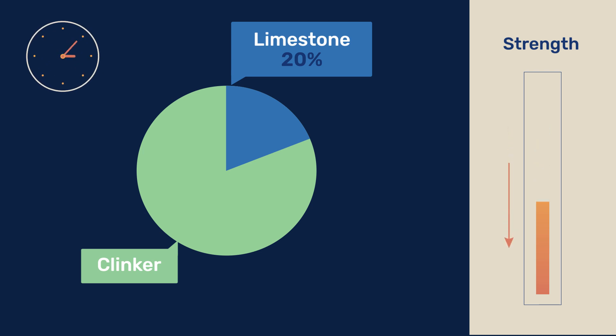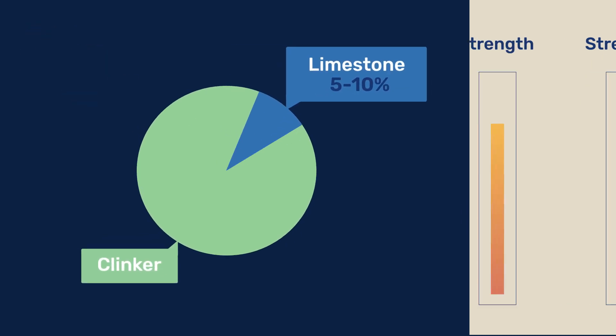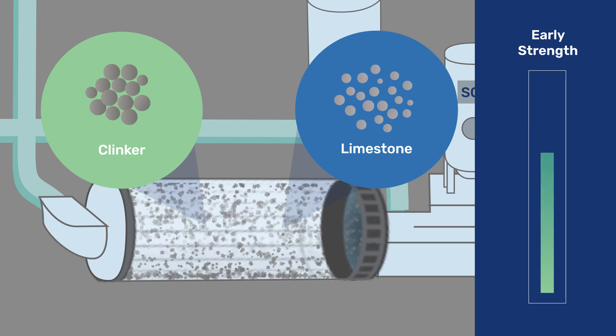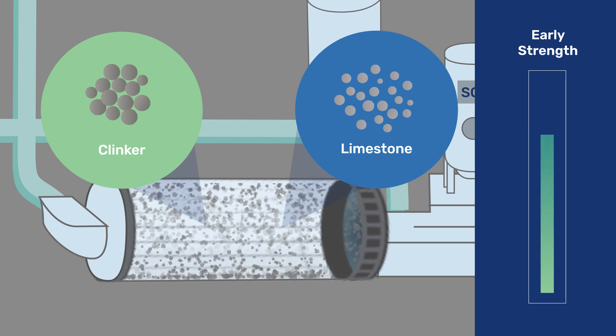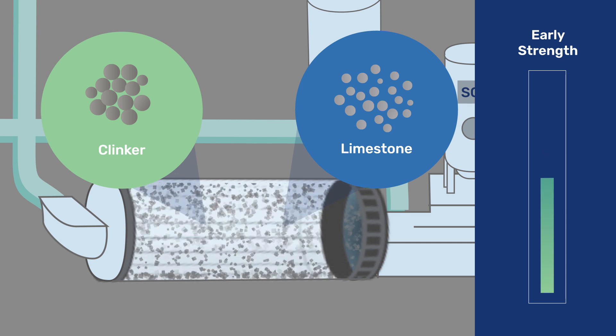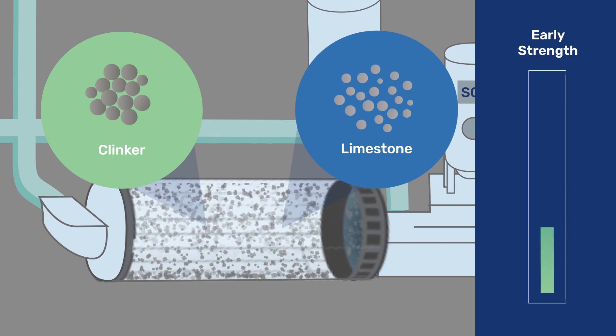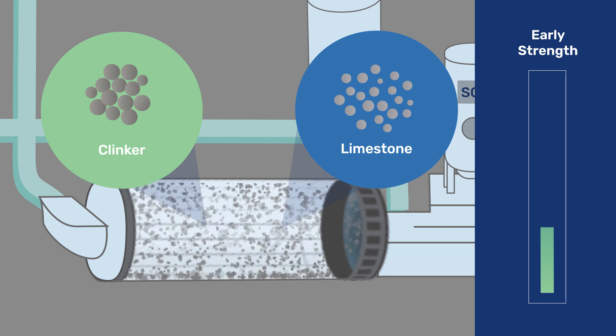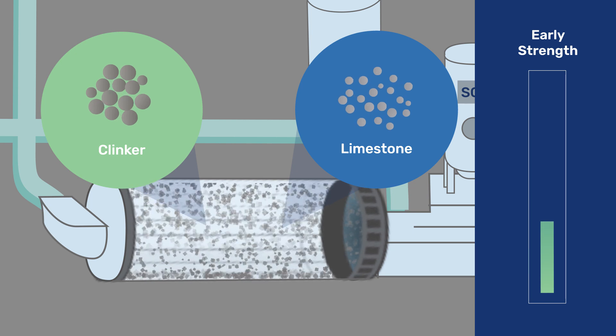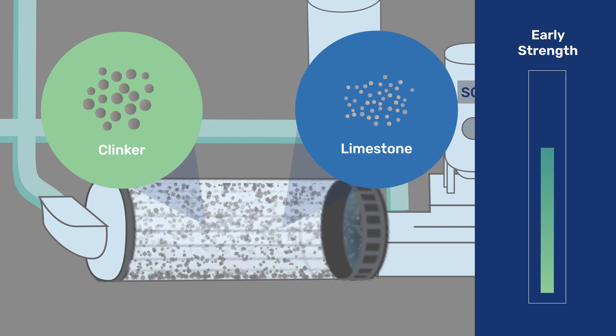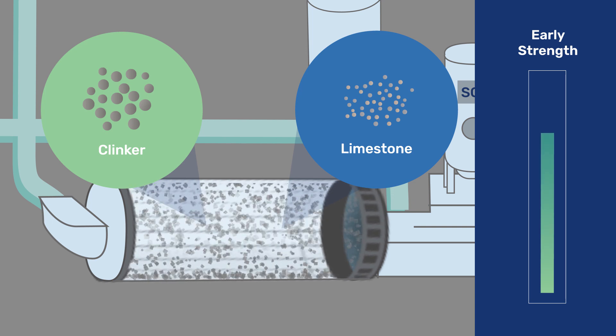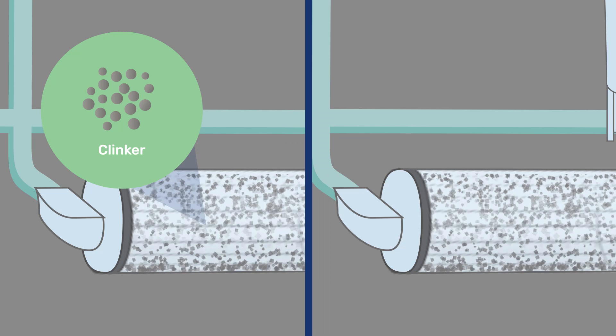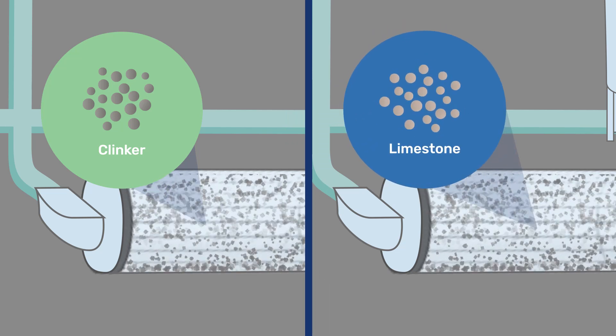For not losing strength at later ages, maximum replacement levels are rather on the order of 5–10%. A downside of the lower stiffness of limestone is that it becomes more difficult to grind the clinker finely in co-grinding, which rapidly becomes a dominating negative factor in early strength development. Thus, when trying to increase early age clinker reactivity through co-grinding, there is a risk of overgrinding, whereby the final cement includes much overground limestone, which is detrimental to fluidity. For this reason, separate grinding of clinker and SCMs is gaining interest.